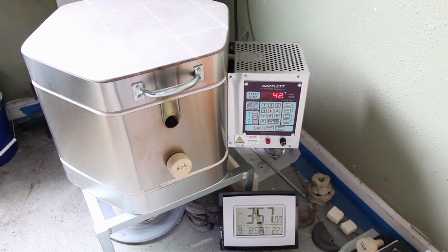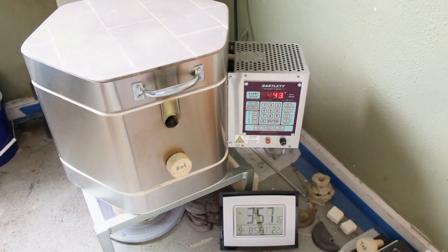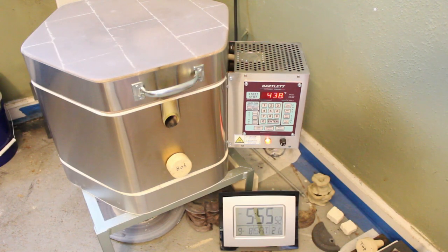The fourth segment goes down to 600°C, also using 600 ramp, and we don't hold. The fifth segment goes slow with 100°C per hour ramp down to 500°C, then we turn the kiln off.